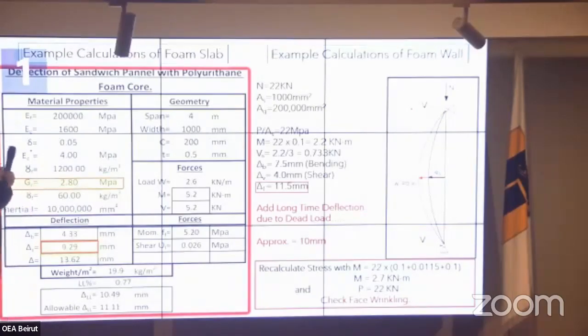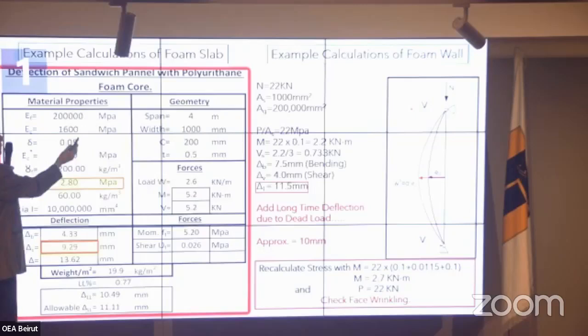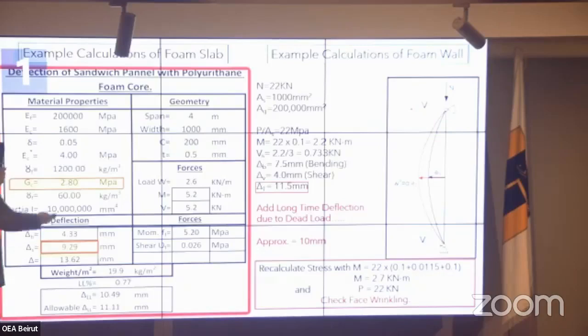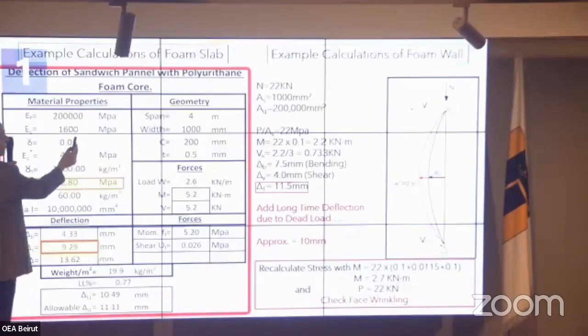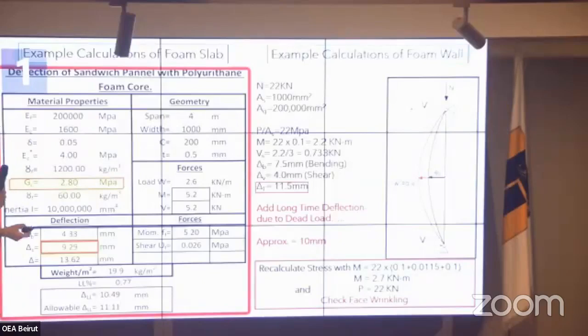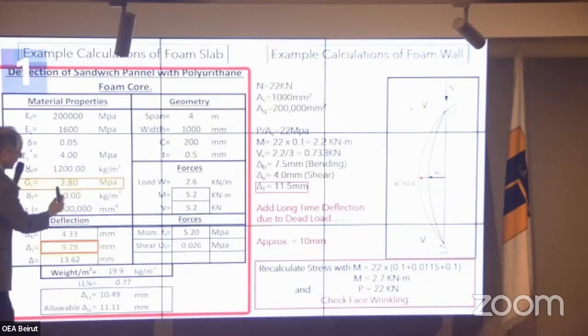while the E of the foam material is usually proportional to the square root of the material percentage. So it's 95% air, void, and 5% material in this foam. And squared, multiplied by this, will end up with a very low modulus of elasticity. If we do this, and we take the shear modulus, which is usually taken around E multiplied by around 1 minus Poisson's ratio, it will end up something like that.